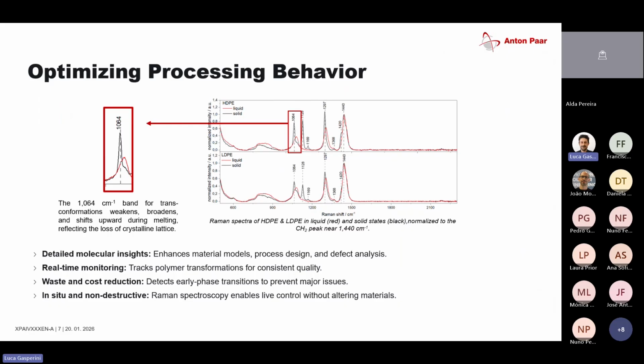And then I brought another example. So here we were taking a look at the crystallinity. We were using HDPE and LDPE samples. We did the rheological analysis, and then we were looking at how the Raman spectrum changes over time. So let's take a look at the HDPE example. Here the red line corresponds with the liquid phase, while the black line corresponds with the solid phase. So you can see there was some melting going on.